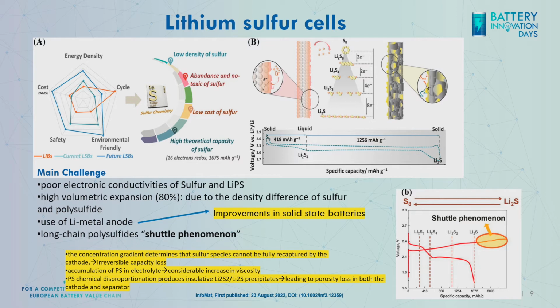Theoretically, it can be 5 times the one of lithium-ion, and this depends, of course, on the lightness of sulfur, and the double capacity, as each sulfur atom can be reduced using a double amount of electrons compared to the elements of lithium-ion. This is quite environmentally friendly because sulfur is very low cost, very highly abundant, is everywhere. We have no trouble to get it. It is also a side product of oil production, so we have a lot. So it's very simple, but why is it not already on the market? If it's so simple, because we still have a lot of issues to be solved.